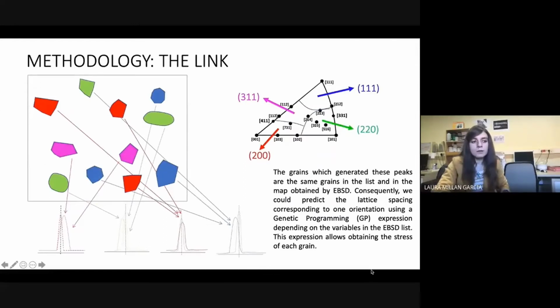The grains which generate the peaks are the same as the grains in the list obtained by electron backscattering diffraction. So we found this link between the two techniques. Consequently, it was possible to predict the lattice spacing corresponding to one orientation using a genetic programming expression depending on the variables in the electron backscattering diffraction. We chose the 111 peak profile. This expression allows obtaining the stress of each grain.